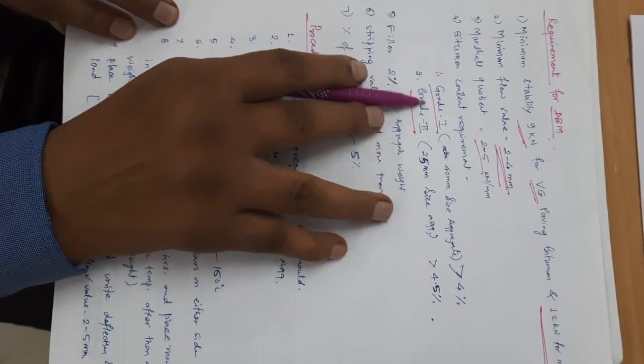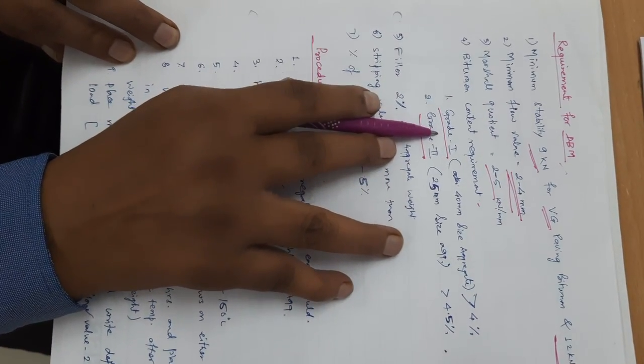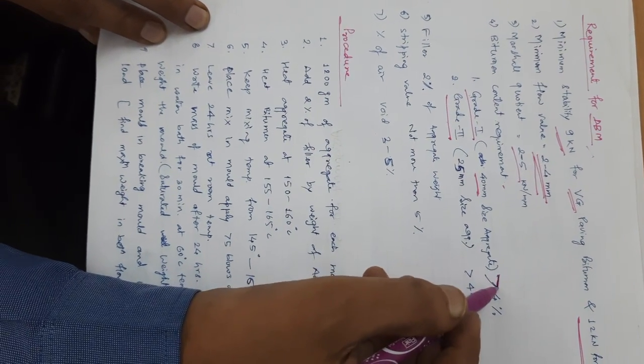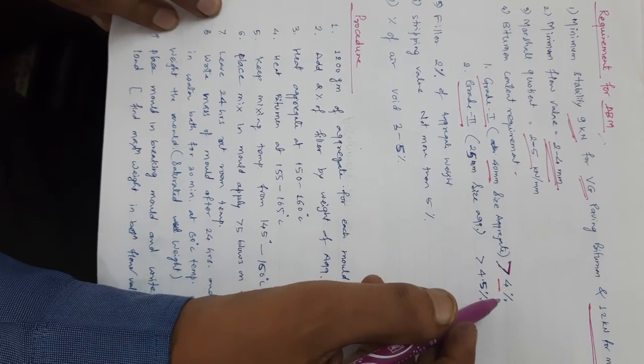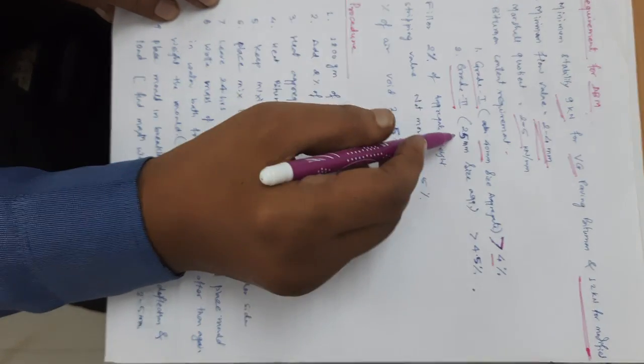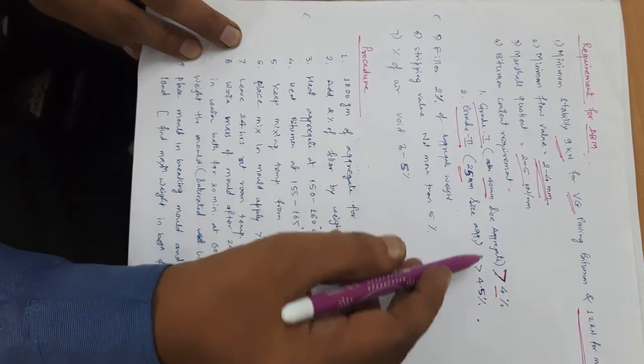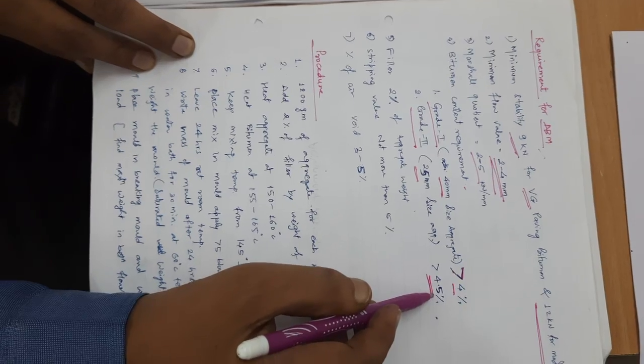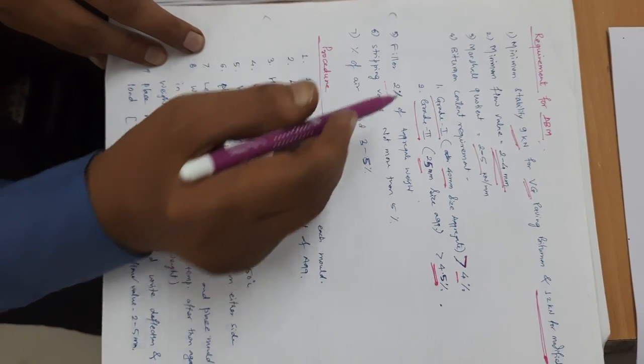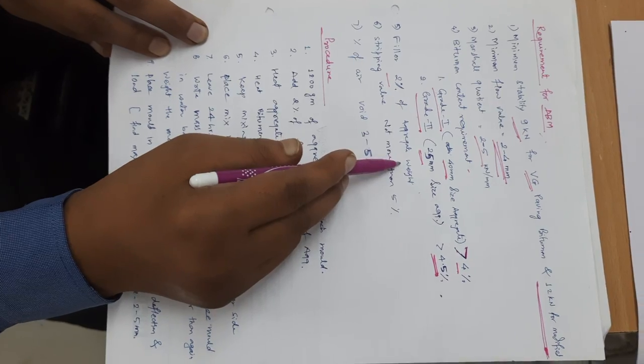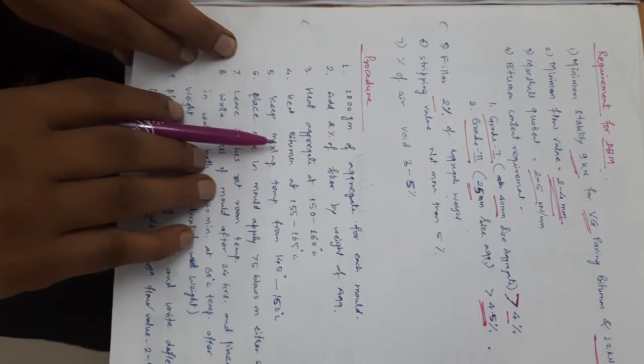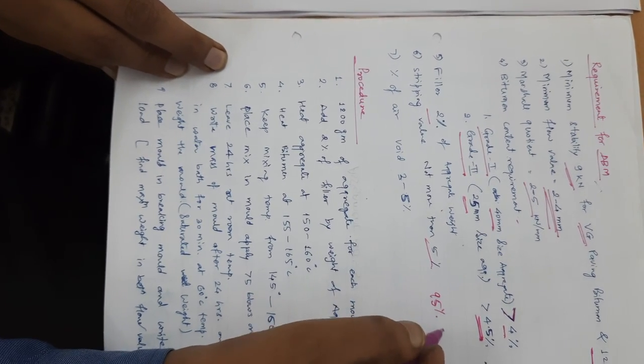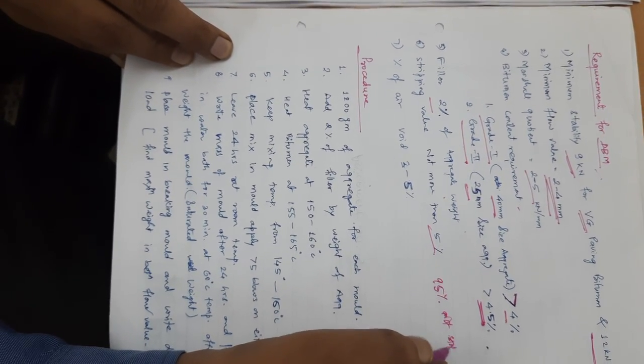Here we are going to use two types of grade. Grade 1 will be used for 40 mm size of aggregate, and for that 40 mm size aggregate we have to use 4% bitumen. For Grade 2, for 20 mm size of aggregate, we are going to use 4.5% of the bitumen by original weight. In both grades, we are going to use 2% filler by weight of aggregate. The stripping value should not be more than 5%, meaning that 95% of aggregate should not be stripped.